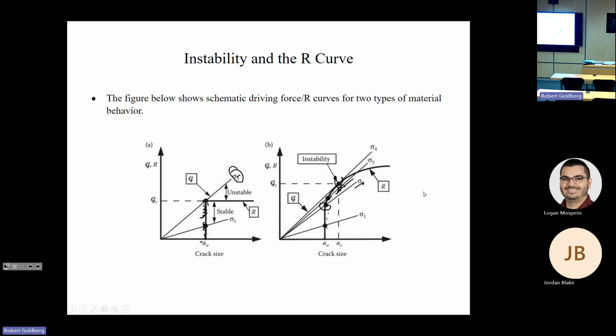curve. So what happens here is it becomes unstable, because once you get to this point, all of a sudden now your driving force, the slope of this sigma 4 line, is greater than the slope of this resistance curve. So this is the point where finally, once you reach sigma 4, the rate of increase in your driving force is greater than the rate of increase of your resistance, and that's what leads to the growth and the unstable growth of your crack.